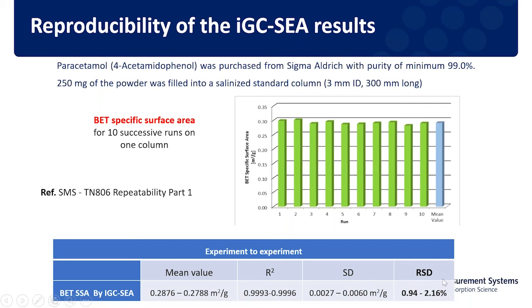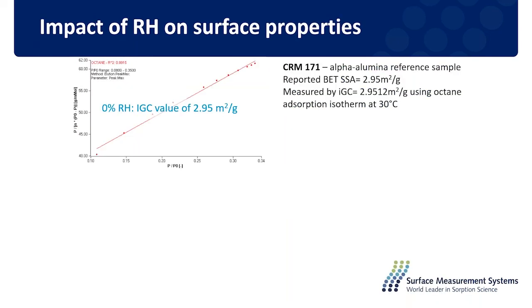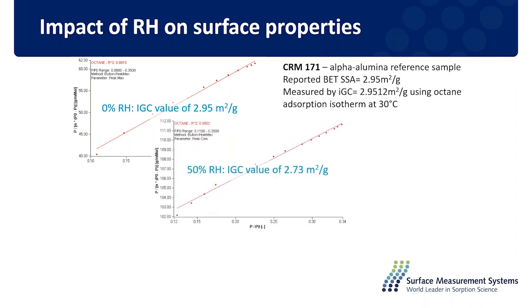For the relative standard deviation, we used 22 columns, so varying the column, the worst was around 2% and the best was less than 1% relative standard deviation. So the technique, like every chromatographic technique, has excellent reproducibility. It's very accurate, and you can measure surface area and surface energy very accurately. A huge benefit is also that we can measure the impact of relative humidity on the different surface properties, like surface area.